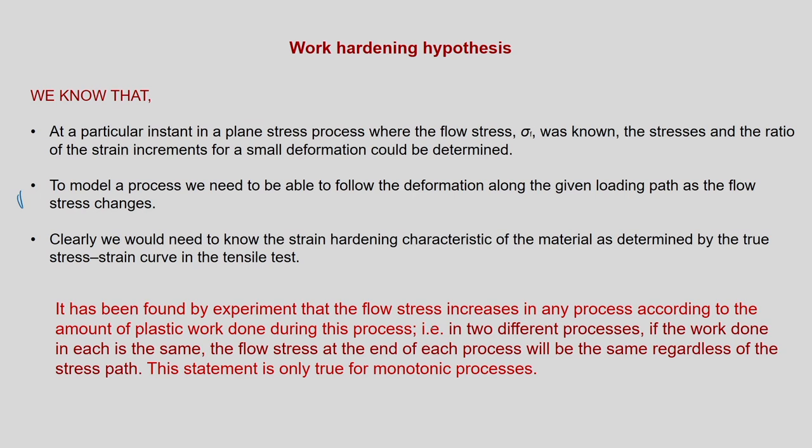That is known. But the main point is, in two different processes, if the work done in each is the same, the flow stress at the end of the process will be the same regardless of the stress path. This statement is true for a monotonic process. Monotonic process, we already discussed, means strain keeps on increasing. So, in two different processes, if the work done in each is the same, suppose you have a uniaxial tensile test and another plane stress process, we can say these are two different processes. If the work done in each is the same, then the flow stresses are going to be the same in these two processes at that particular stage. That is what the hypothesis is about.